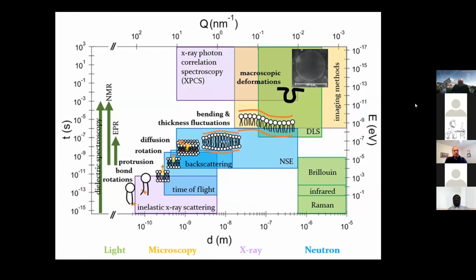So this is this rather busy plot. I'll just draw your attention to the x-axis at the bottom, which is the length scale that we probe in meters, and the left axis, the y-axis, is the time scales we probe. Neutron spin echo allows us to probe large-scale slow motions, and you can see that bending and thickness fluctuations are right there in the sweet spot of neutron spin echo and not accessible by others.